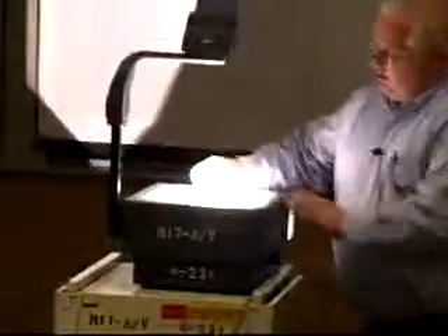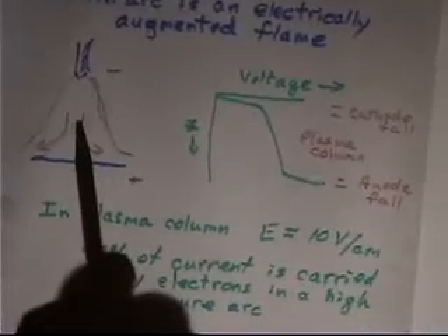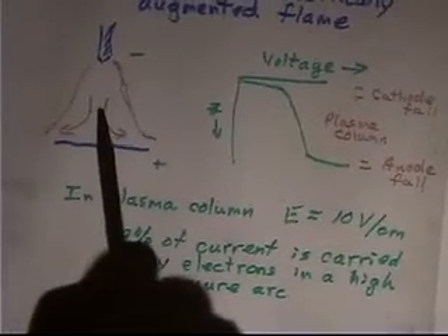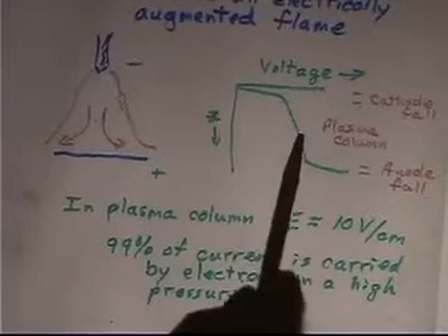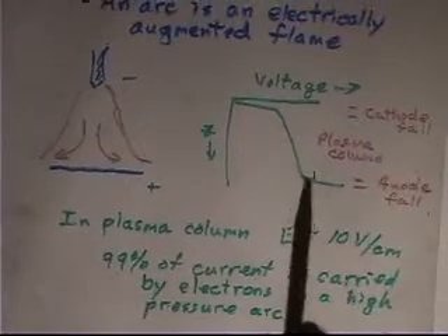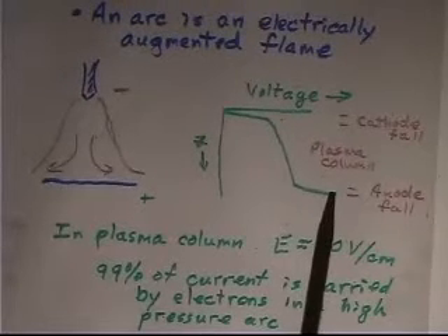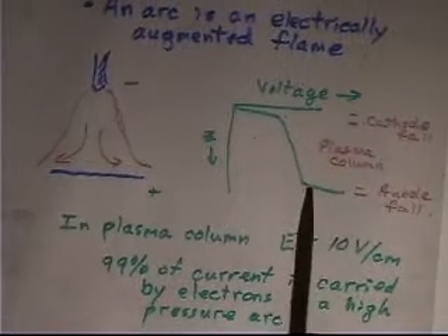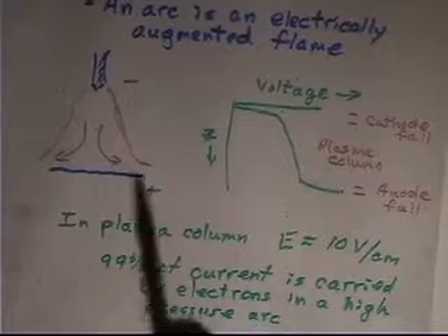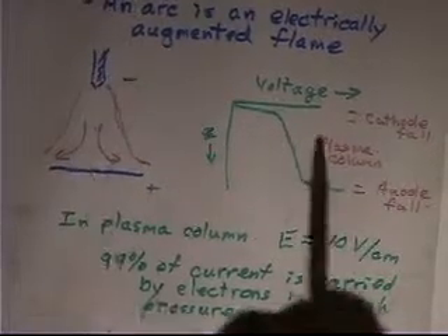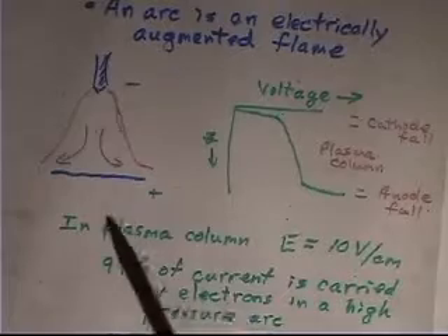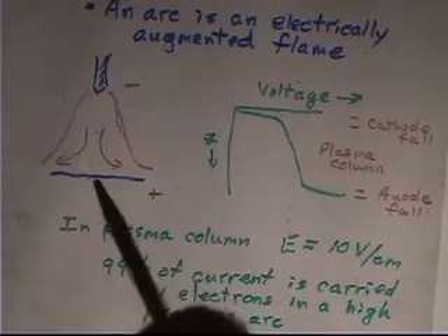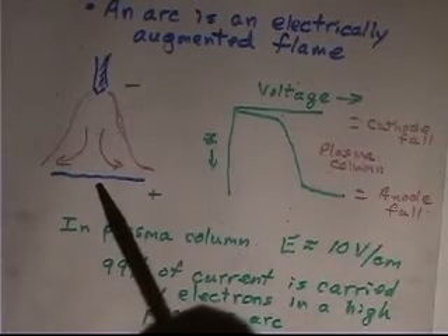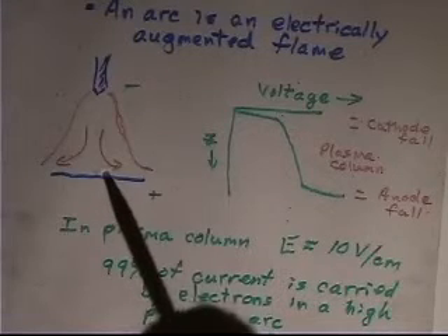Well, the anode voltage drop we already talked about. The anode voltage drop is the fact that if my electron is sitting up here with 1 volt of equivalent Thomson thermal energy, it's in the middle of the plasma column. In order to get down into the metal, it has to punch through this voltage that is created by the cold gas in the boundary layer at the surface of the anode. And I have to apply enough voltage to the arc to accelerate that electron through this cold, very, very weakly ionized plasma layer. Now, that's the layer that the physicists can deal with, okay?